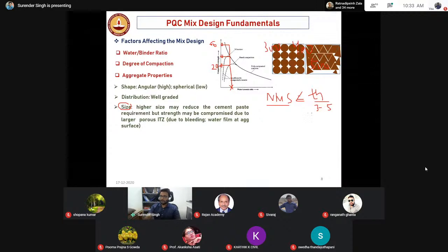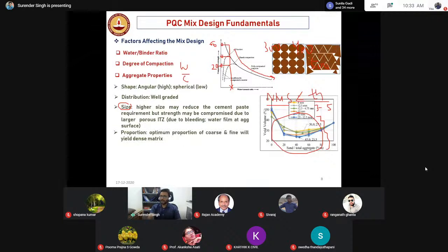Why? Because if you increase the size, obviously the cement paste requirement will be lesser, but the bonding between the cement paste and your aggregate will be very, very poor, right? Because bleeding water will be there, and if the bleeding water is coming, the water will be increasing, so the water by cement ratio will be increasing, and you will be getting the lower strength. And similarly, the ratio of coarse aggregate to fine aggregate is an important parameter.